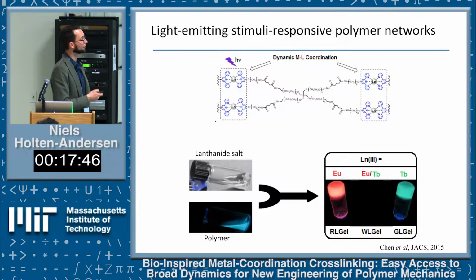So what we did is work with this same type of polymer, switching up the ligand a little bit to something we know binds lanthanide ions very strongly. We showed that if you just have the polymer mixed into solvent without any lanthanide ions, the polymer by itself will emit blue light when excited. If you cross-link it with europium ions, you get a red emitting gel. If you cross-link it with terbium ions, you get a green-blue emitting gel.